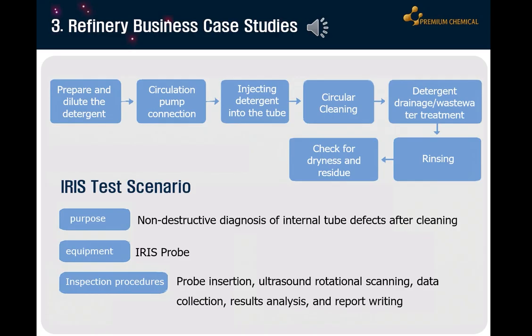The chemical cleaning process involves: 1. Dilute the prepared cleaning agent with water. 2. Connect the air fin cooler to the circulation pump using a high-pressure hose. 3. Operate the circulation pump to inject the cleaning agent into the tube. 4. Operate the pump for a specified period of time to perform the circulating cleaning. 5. Once the process is complete, drain the cleaning agent from the air fin cooler for wastewater treatment. 6. Continue rinsing with clean water. 7. After drying, inspect the cleaning quality by selecting one of the following: temperature changes, flow rate changes, or visual inspection.